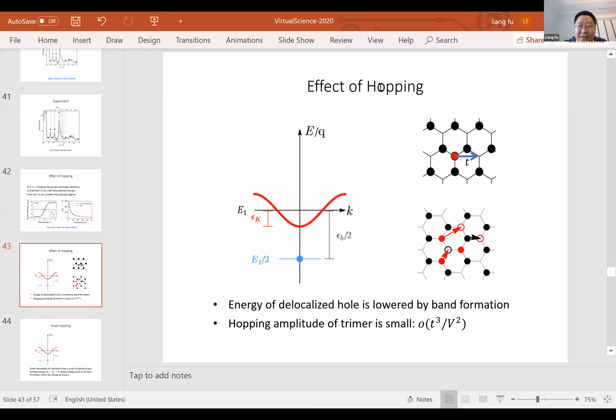So when we turn on the quantum mechanical hopping, it has several effects. First, the single charges, the doped holes, now can hop around and they form a dispersive band. Because of the presence of the band, the energy cost of adding a delocalized hole is now lowered, right? It's lowered by the kinetic energy of this itinerant hole. On the other hand, if we think about the trimers, because it is a composite excitation, to hop a trimer it requires a third order process, right? Each charge that forms this trimer has to hop individually, and therefore the hopping amplitude of a trimer is small. It's t to the power of three divided by the interaction energy V squared. So the hopping amplitude of trimers can be neglected to the leading order.